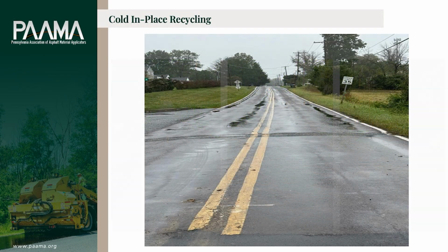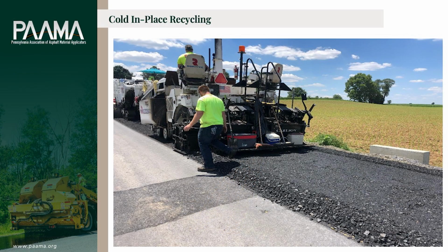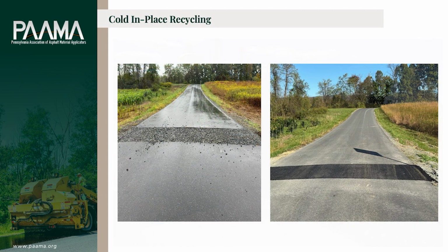Cross pipes. Replacing the cross pipes is important, but do them the year before, give them a chance to settle. Otherwise, we come in, we recycle the road, put an overlay on, and the next thing you've got is a settlement where the cross pipe was and the aggregates have settled down. So get them done a year prior, and then when you recycle you take out any imperfections in that cross trench. If you don't, you have a situation like this. Brand new road, cross pipe failed after it was recycled and overlaid, and now you've got to come in and put a patch in the road when you put your new cross pipe in.